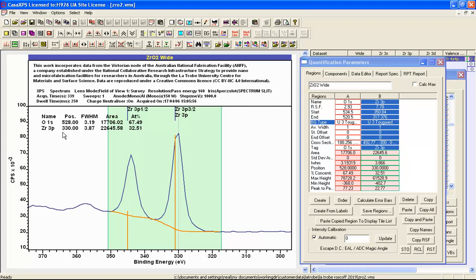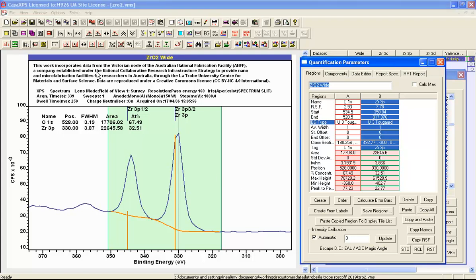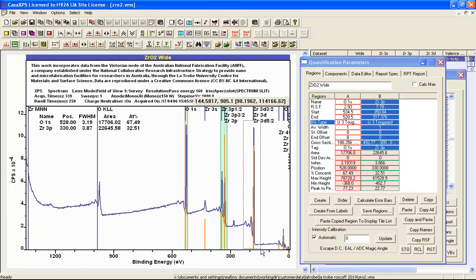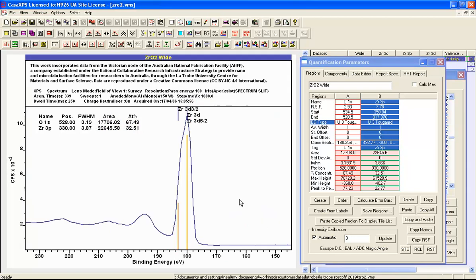There may be reasons why some of these other zirconium peaks would be chosen in preference to the zirconium 3p. For example, here we have the zirconium 3d and it's a doublet, but the resolution with which these data were measured means that there's a single peak. In some ways this would be more in line with the oxygen peak, which again had a single peak effectively that could be identified using a quantification region.